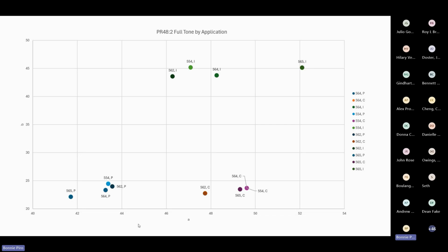And then the plastics application, which makes a whole lot of sense because there is so little dispersion time and energy employed during that particular process. So there is less opportunity for dispersing these particular pigments, so that the color development is not as full as in other areas where you have more energy input into both the formulation as well as the media choice.